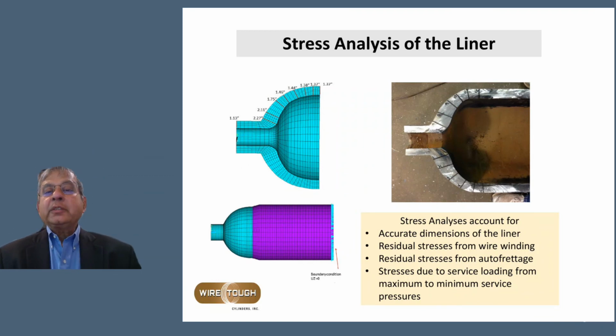Then we move to the stress analysis of the liner, which is a necessary part of the ASME certification. The stress analysis must account for very accurate dimensions of the liner, residual stresses from the wire winding, and residual stresses from autofrettage. Autofrettage is a process in which we subject the vessel to pressure levels of almost 2 times the maximum operating pressures. What that does is basically plastically deform the liner. When you remove the pressure, the wire wrap, which remains elastic, collapses onto the body of the liner, and it creates a lot of compressive stresses that actually decrease the maximum stress that the liner wall sees when it is subjected to the service pressures. So we also have to account for service loading from maximum to minimum service pressures.